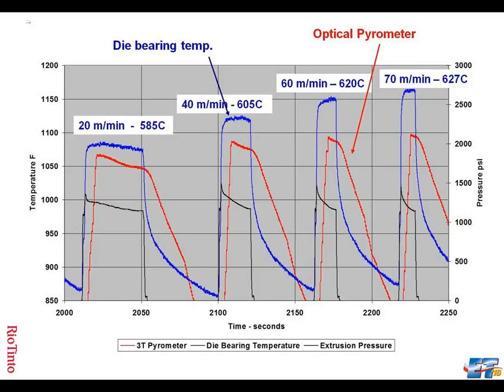This is measuring bearing temperature, the temperature of the bearing at the exit of the press, and the red plot shows the optical pyrometer reading. It shows us that what we measure at the exit of the press is substantially colder than what's happening at the bearing. What we wanted to do with this paper was to find the rules which relate optical pyrometer measurements to what is happening at the die bearing. If we can calculate the bearing temperature from optical pyrometer values, we're getting so much closer to maximizing productivity and maximizing speed.